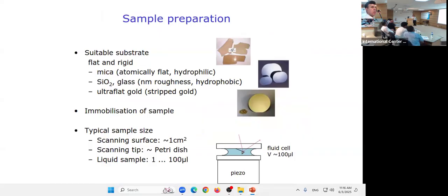Now, Saira and Tasmina will show you how to prepare the sample after this lecture, tomorrow afternoon. But you know that in most cases we use a mica surface, which is an atomically flat surface. We load our sample on the mica, or there are some silicon wafers, but mica is atomically flat. So if your particle is very small and you want very minute detail, you can use the mica surface. But if your particle size is a bit bigger and you do not need that, you can use a silicon wafer, because mica is a bit more expensive.